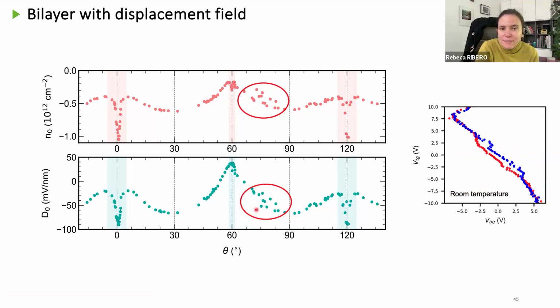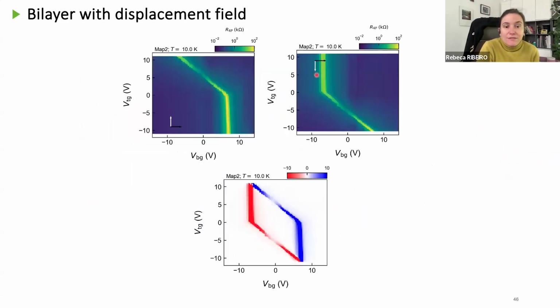So if we take the sample in that specific alignment, and we go to low temperatures, we can observe that, in fact, yes, it's a hysteretic loop. It's a very well-defined hysteretic loop that has been recently associated with ferroelectricity, with a ferroelectric behavior. So what it means is that our system is being polarized, the position of the layers, the control of the alignment between the layers, take them to a metastable position where you have dipoles, and these dipoles are getting reversed, getting switched by the gate. So if you go in one direction, you get your dipole in one alignment. If you go in the opposite direction, you get them to switch in the opposite alignment.